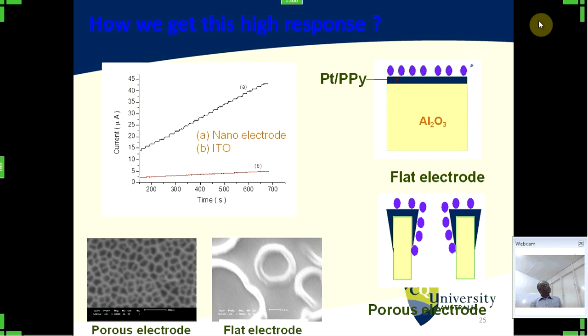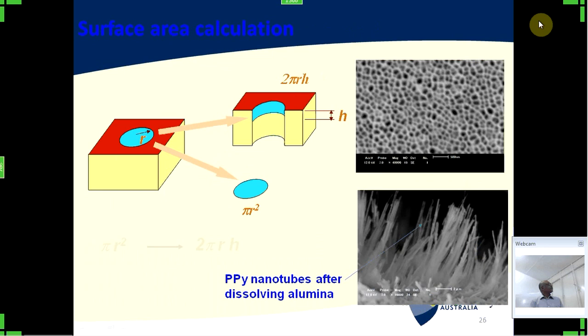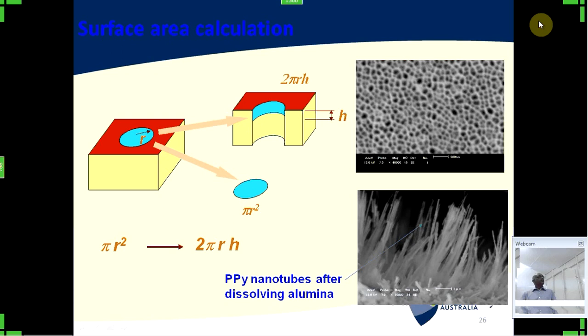Why does it happen? As I mentioned earlier, this is the normal one. If you have a hole and polypyrrole deposited inside the tube, you get more and more glucose molecules getting entrapped into the polypyrrole network. That's why you get a higher response here. To see it experimentally, we dissolved the alumina in sodium hydroxide at very low concentration, 0.01 or so. Polypyrrole nanotubes developed in the membrane, right? Once this yellow color part is dissolved, you get only this brown color part and this green color part. So these are the tubes, the green color one. This is actually not to proportion, it is much, much longer there. That's why you can see them very long.